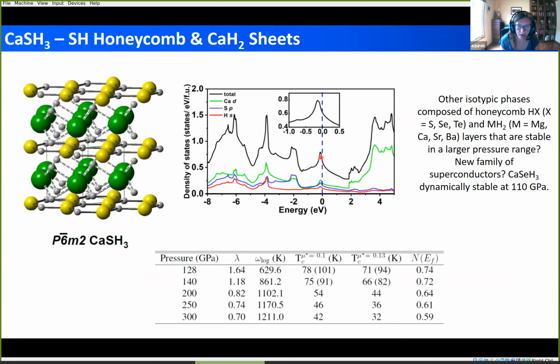We also find that you have this Van Hove singularity near the Fermi level, just like we do in H3S. However, because this is a two-dimensional version instead of a three-dimensional version, we find lower TCs than H3S, going up to potentially 100 Kelvin at about 78 or 80 gigapascals.